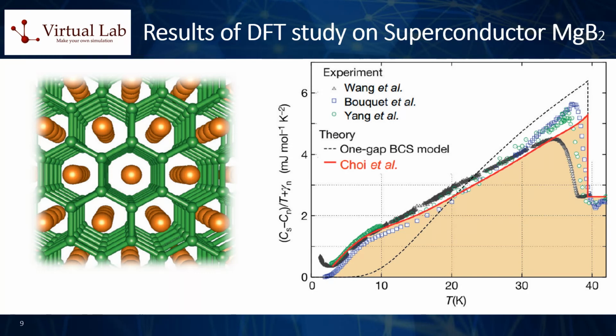In particular, there is a good consensus on the value of the critical temperature of 39 Kelvin, where the discontinuity in the heat capacity occurs and below which the material behaves as a superconductor. The dashed black line, on the other hand, representing the predictions obtained via the simpler BCS model applied to magnesium diboride, is not able to reproduce all the detailed features of this heat capacity plot as accurately as the DFT calculations themselves.